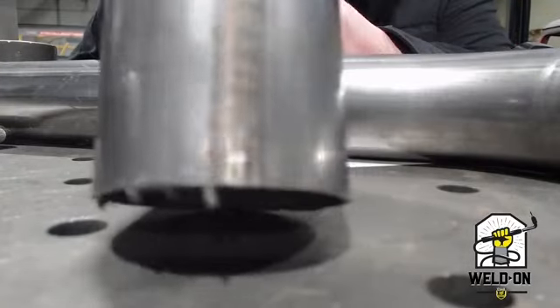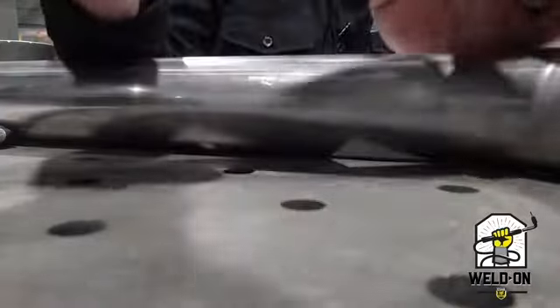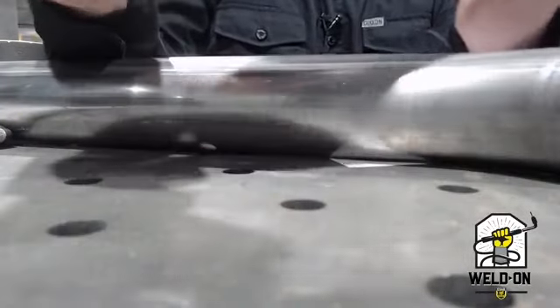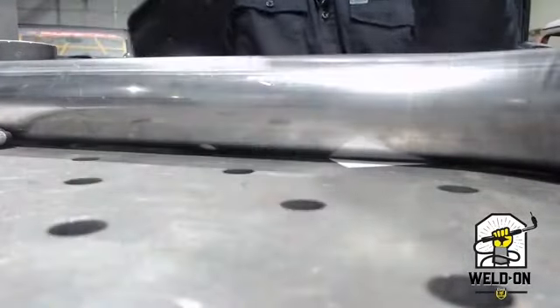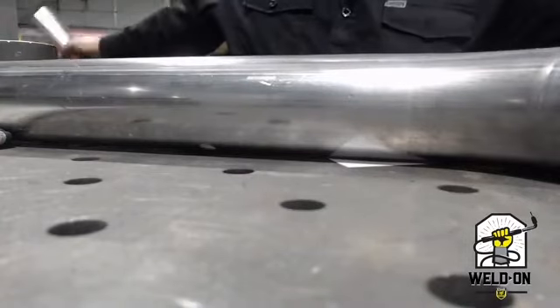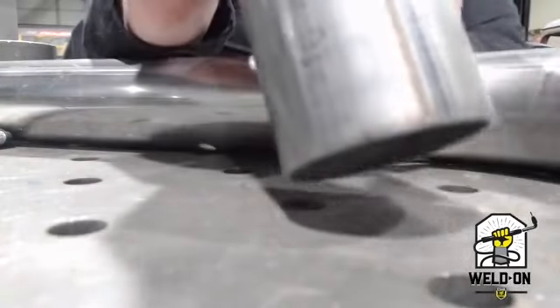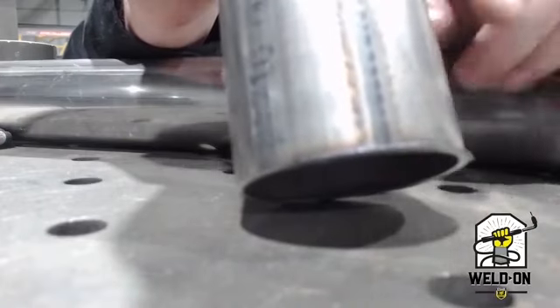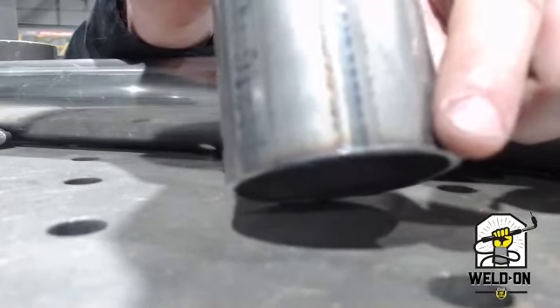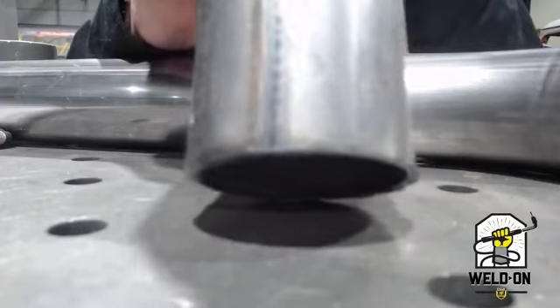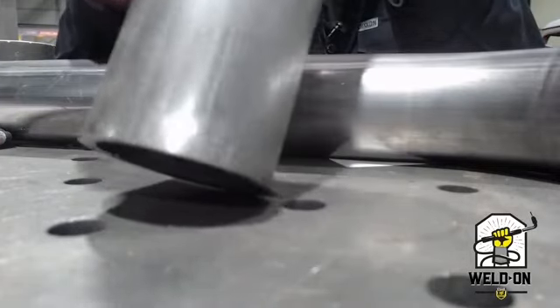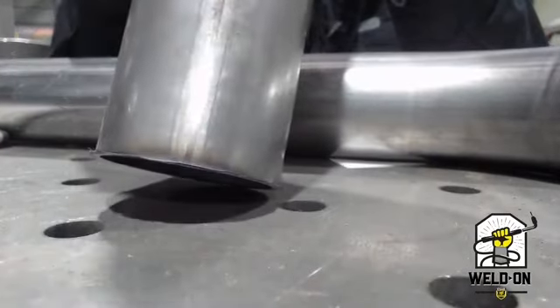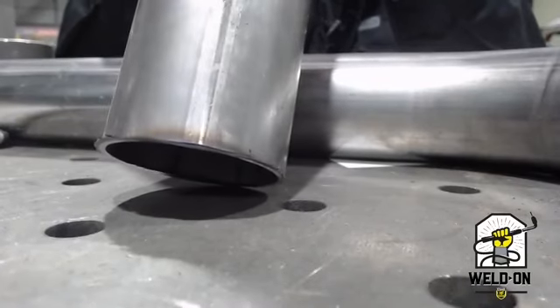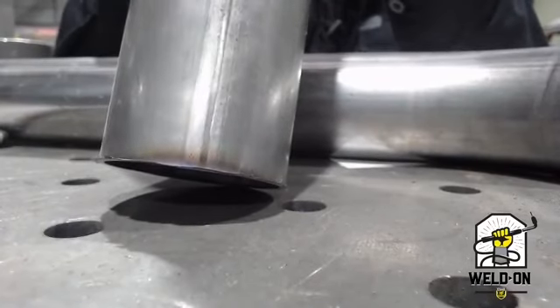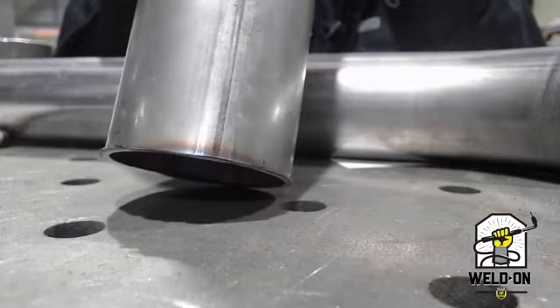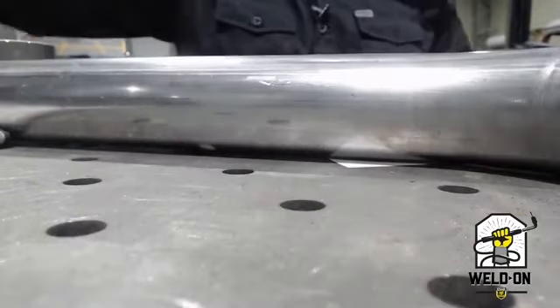But when you roll around to the opposite side where the big burr is from the cut, I'm trying to find it with my hand here. Oh, wait, sorry, I'm showing you the wrong piece of pipe. There we go. So you can see on this side that little brown edge that is basically popping up into this pipe? And as we roll around to the back side, it's going to become even more evident. You can see that that has actually started to boil some of the chromium out of this particular pipe.